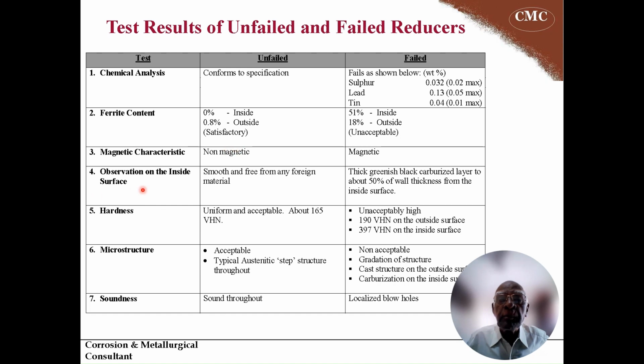The ferrite content varies from inside to outside. Unacceptable microstructure, ferrite content. Similarly, magnetic characteristic. Incoloy 800H is a non-magnetic austenitic stainless steel variety, hence it is non-magnetic, whereas the failed one is magnetic, and this itself shows there is a lot of ferrite content due to the compositional variations. The observation on the inside surface: smooth and free from any foreign material, that is so far as the unfailed one. Whereas the failed one has a thick greenish black carburized layer to about 50% of wall thickness. The carburization leads to brittleness and it is very easy to crack.